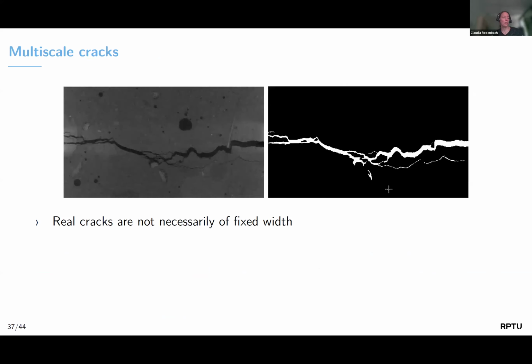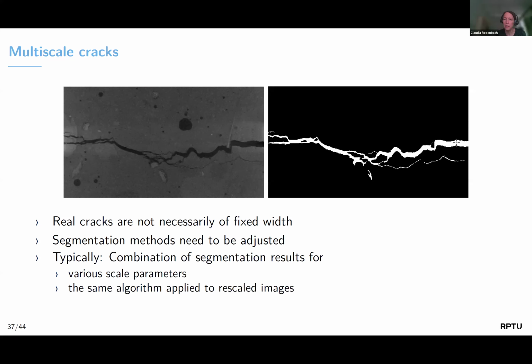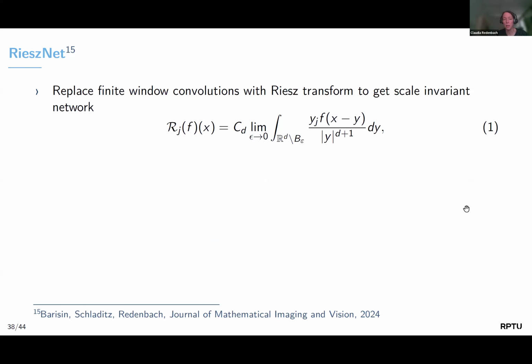Furthermore, I also mentioned these multi-scale cracks. So we already discussed that probably you should choose different scale parameters. If you do that, so if you run your method multiple times with different scale parameters to detect either the thin or the thick crack, that of course increases the runtime. So therefore, we were interested in a method that could segment multi-scale cracks in a single run. And this was indeed possible by a modification of the network that we are using.